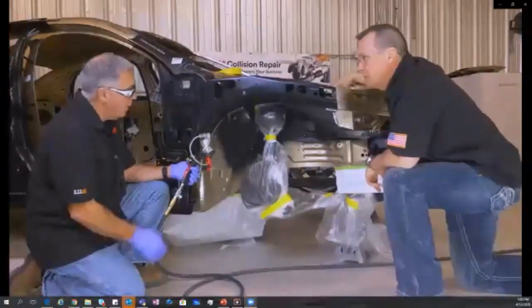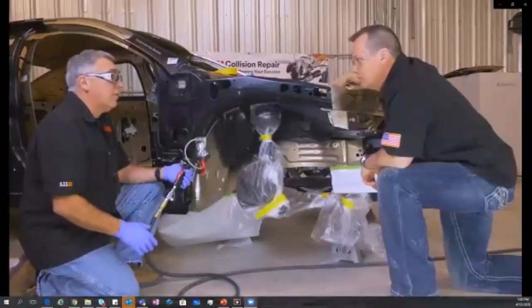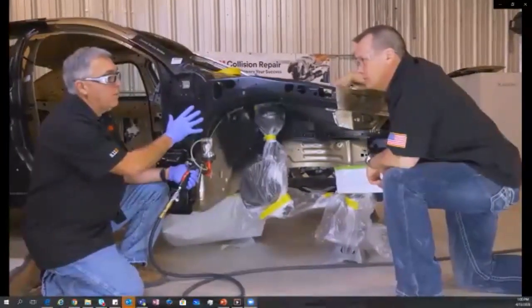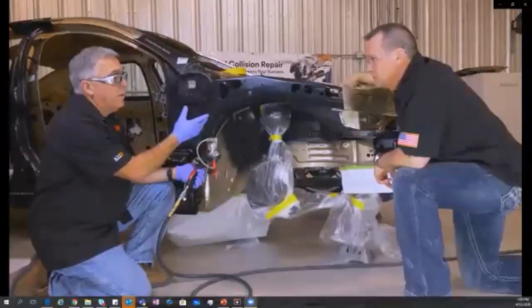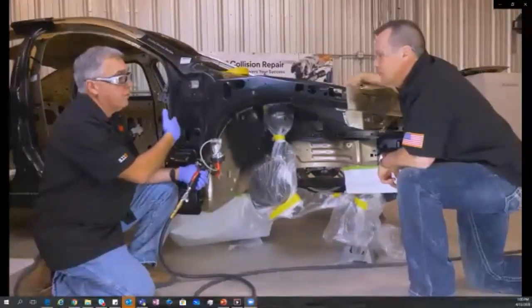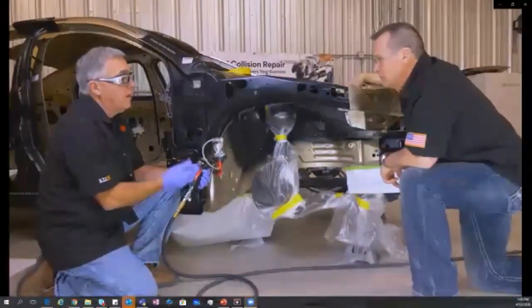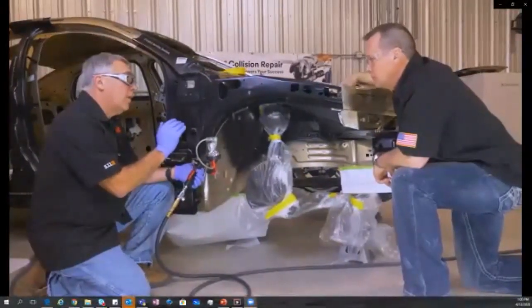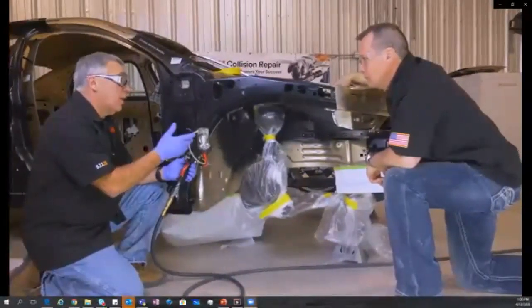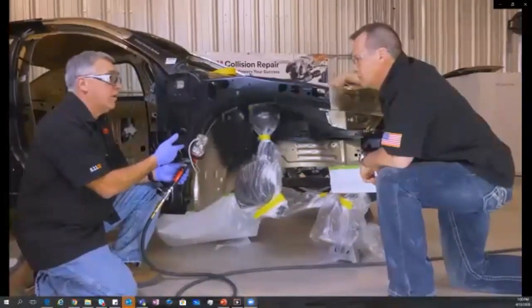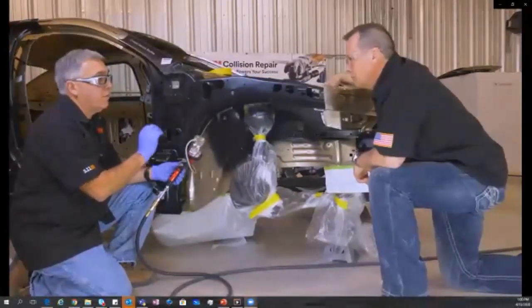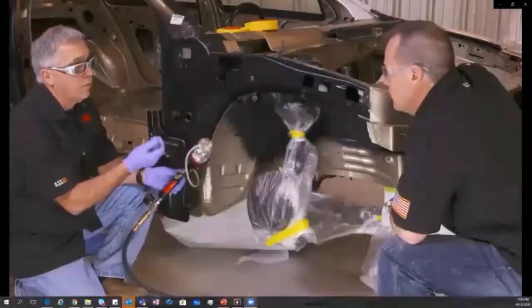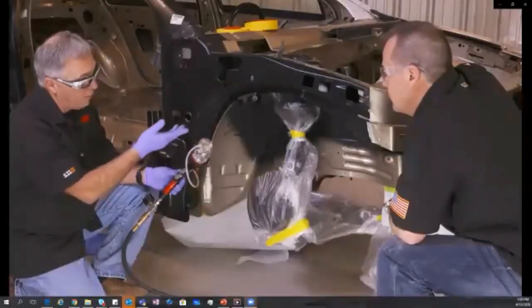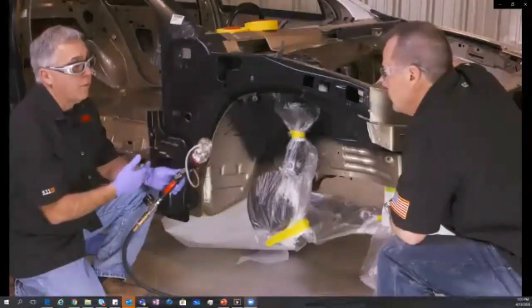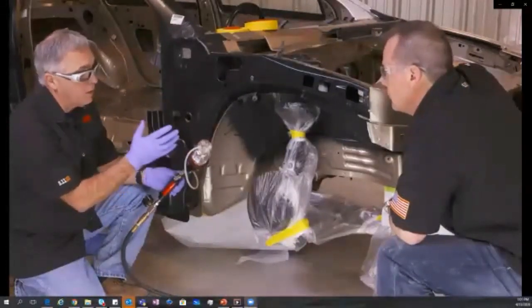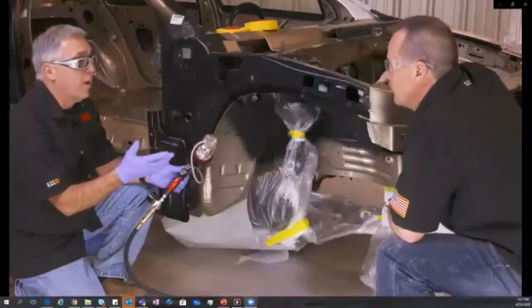Yeah, another great spot for this, Sean, if you want to think about it, is of course this car was on a repair bench, right? So it was clamped in quad clamps underneath here, so there's four clamps that were holding us up on the pinch welds, and we know that area had to be cleaned off. So again, that's important that you go ahead and use some undercoating. This is a paintable material, so I can go ahead and clean that up, dress it, scuff it, and I can put the undercoating on those areas. And when it dries, the painter can go ahead and paint the color back on top of this with no problem. So another great application that guys oftentimes may forget about or just may not get time to do.